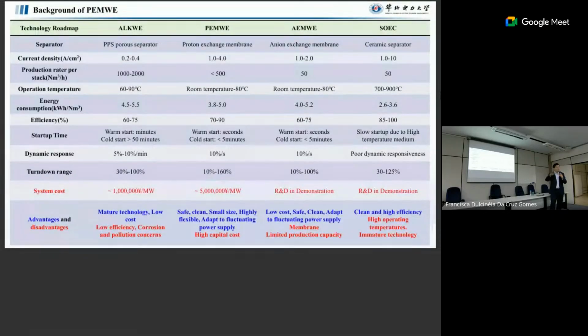But if we have a low load of electricity, then the reaction is very slow. We have a small amount of oxygen produced. At this time, the hydrogen will get mixed with oxygen, then it becomes dangerous. So that's why this system cannot work at a low range of electricity load. And also, because we use this electrolyte, KOH, we have a higher ohmic resistance, and also because the system is not as compact as PEM, for example, there is a long diffusion distance. That's why we have a higher power consumption.